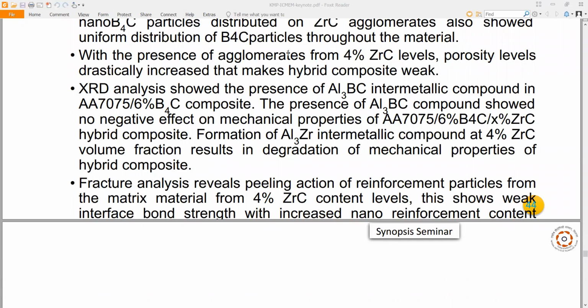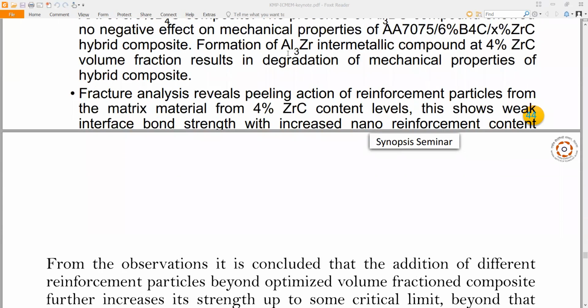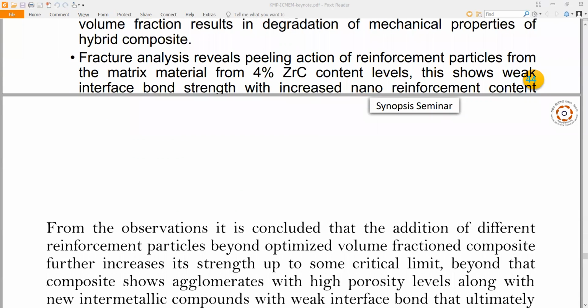Then XRD analysis showed the presence of Al3BC intermetallic compound in AA7075, 6% B4C composite. The presence of Al3BC compound showed no negative effect on mechanical properties. Formation of Al3Zr intermetallic compound at 4% ZrC volume results in degradation of mechanical properties of the hybrid composite, but this happens at 4% of ZrC. And fracture analysis reveals peeling action of reinforcement particles from the matrix material from 4% ZrC content levels.